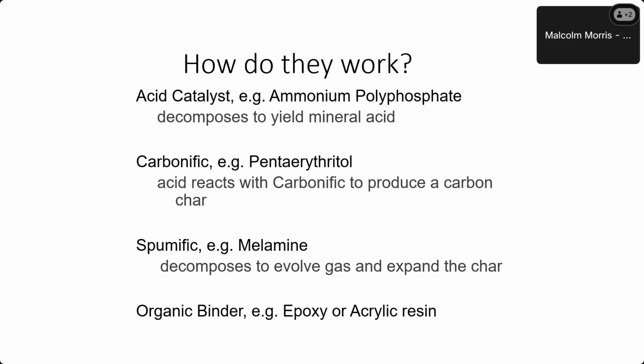And then what we call spumific, which is typically something called melamine, which decomposes to give nitrogen gas in the fire situation, which expands the char up into a foam, and that forms the carbon char. The fourth element there is the organic binder, which the coating is based on. Effectively, as the fire heats up, that binder melts and holds the whole thing together. So you've got this exotic cocktail of melting binder, carbon being formed, and then spumific blowing it up into a foam, a little bit like shaving foam coming out of a can. The whole thing foams up into this wonderful carbon blanket, which will give it an insulating effect.